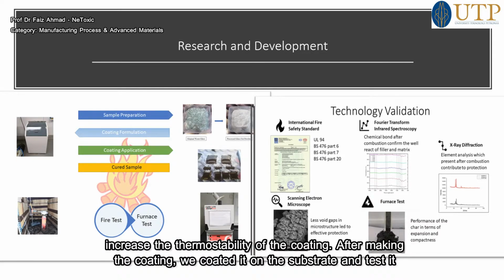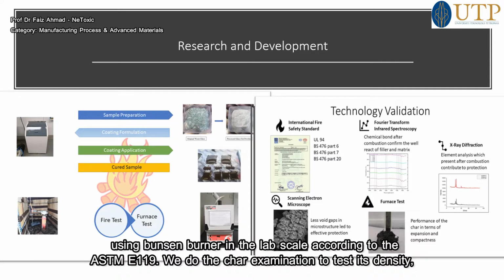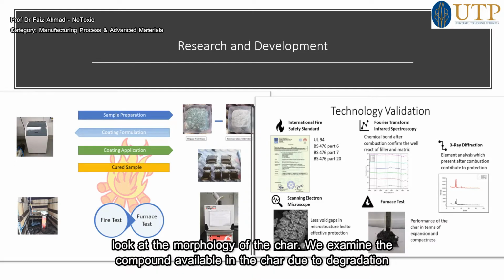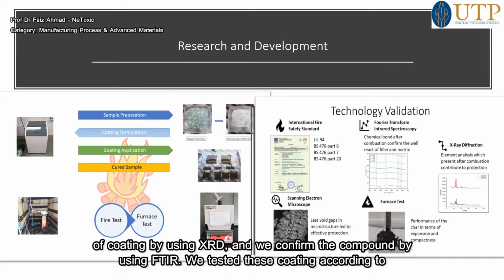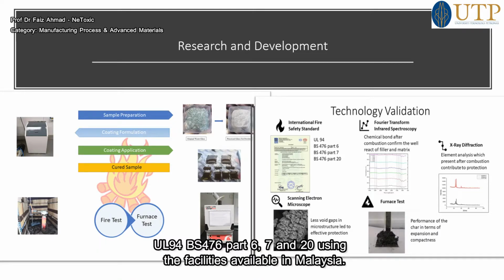After making the coating, we apply this coat on the substrate. We test it using the Bunsen burner at lab scale according to ASTM E119. We do the char examination to test its density. We look at the morphology of the char. We examine the compounds available in the char due to degradation of the coating. We use XRD, and then we confirm these compounds using FTIR. We have also tested these coatings according to UL94, BS 476 Part 6, Part 7 and 20, using the SIRIM facility available in Malaysia.